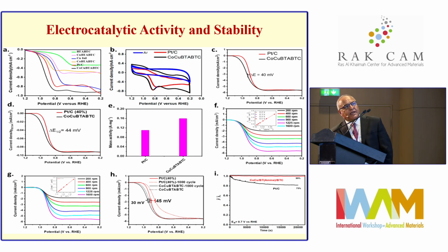You can also calculate the number of electrons that are transferred to each oxygen molecule. And in the bimetallic system, we get exactly 4 electrons, forming the hydroxide ions. And that's not the case for the platinum carbon system. Finally, you can see in terms of the recycling and the stability that the bimetallic has 99% stability, higher compared to the platinum carbon, which only achieves 75%.